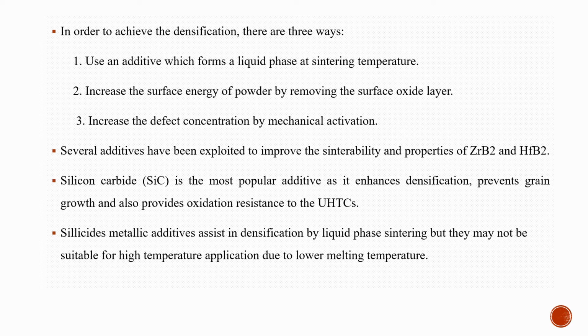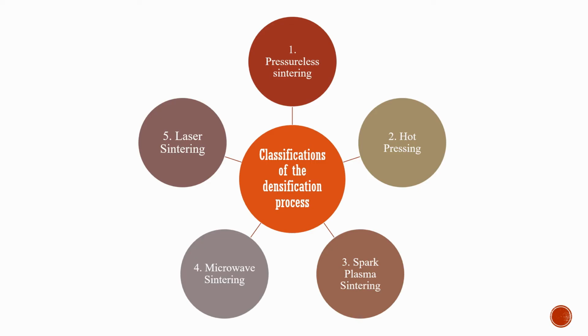Several additives have been exploited to improve the sinterability and properties of zirconium diboride and hafnium diboride. Silicon carbide is the most popular additive as it enhances densification, prevents grain growth and also provides oxidation resistance to the UHTCs. Silicide metallic additives assist in densification by liquid phase sintering, but they may not be suitable for high temperature application due to lower melting temperature. There are 5 classifications of the densification process. 1. Pressureless sintering. 2. Hot pressing. 3. Spark plasma sintering. 4. Microwave sintering. 5. Laser sintering.